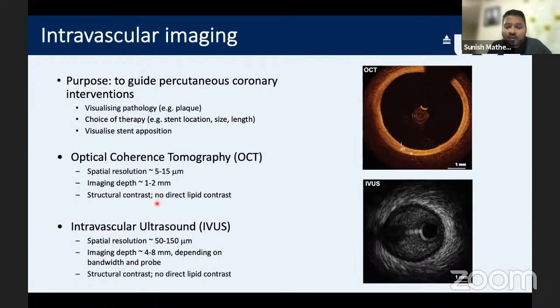The other technique is intravascular ultrasound, which is similar to ultrasound imaging. So you put a probe inside the artery. So instead of light, you're using ultrasound to visualize the artery. As you can see, the resolution is poor, but one advantage is that you can see much deeper inside the tissue. But again, this technique also has the same problem with no specific contrast for lipids. So these are the two state-of-the-art techniques that are being used for intravascular imaging, but they don't have any direct lipid contrast, so you can't view the plaque very clearly.